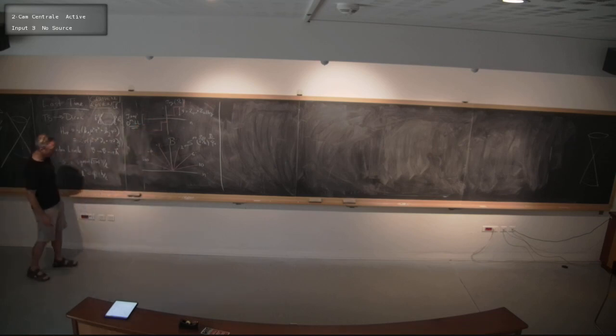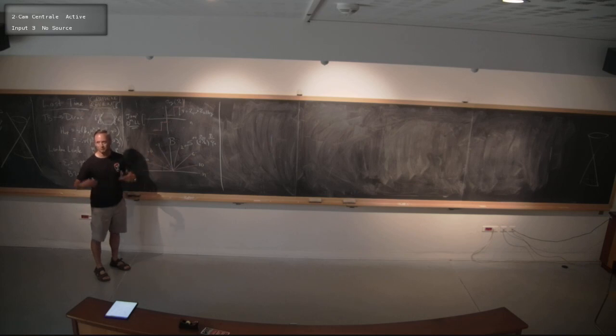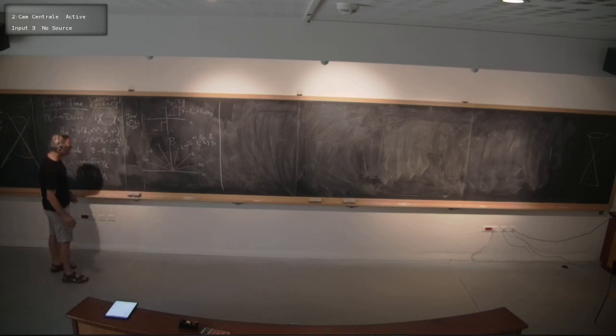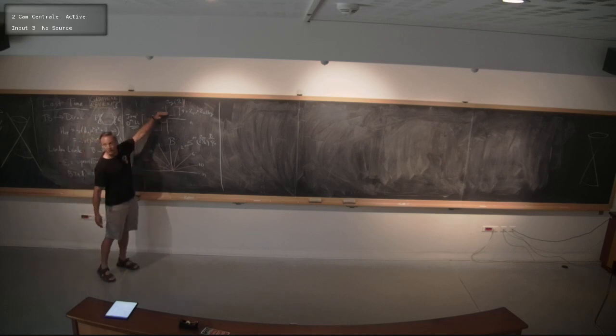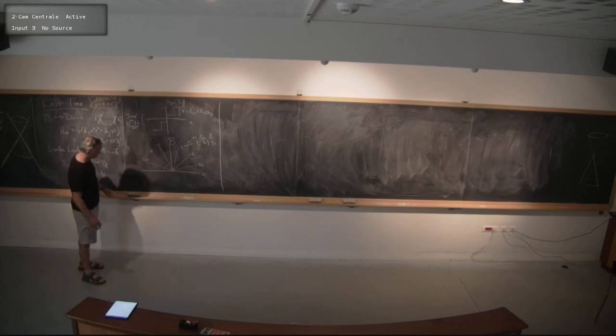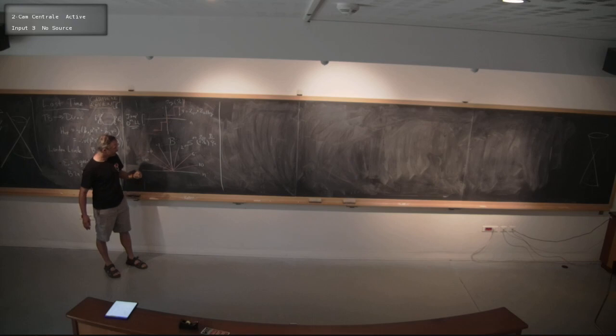One can also see this in what's called a fan diagram. This is advantageous because you can make this kind of diagram even when you're not at quite low enough temperature or high enough fields to see full quantization. You just see oscillations in the resistivity, and you mark, for example, the minima in the resistivity, which generally occur between Landau levels. These will follow straight lines in the magnetic field-density plane, corresponding to that condition of filling Landau levels. I got a little confused last time by how I'd labeled them.